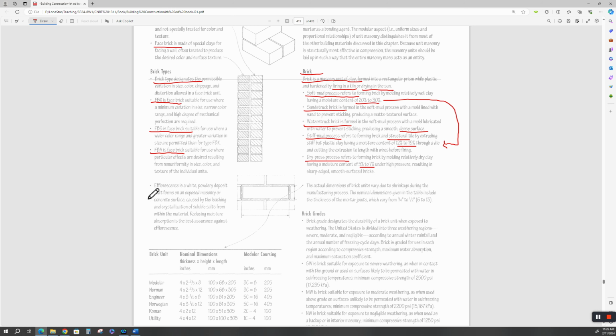Efflorescence. This is something you've got to worry about. It's a white powdery deposit that forms on an exposed masonry or concrete surface. It's not just for masonry, it's also for concrete. And it's caused by the leaching and crystallization of soluble salts from within the material. Now, we're not using salt water to mix the cement, I told you that. But you do have natural salts in the aggregates, the cement, the additives, and reducing moisture absorption is the best assurance against efflorescence.